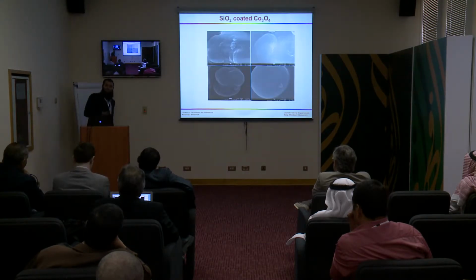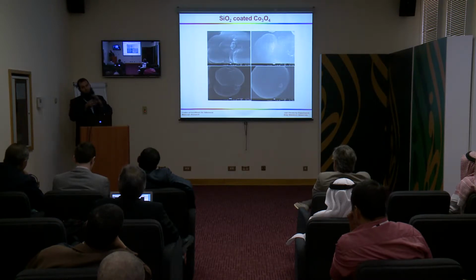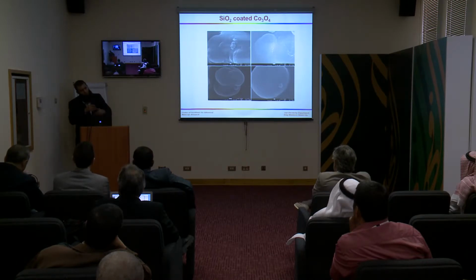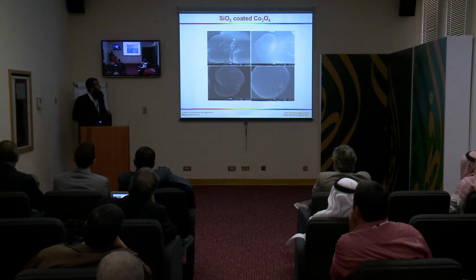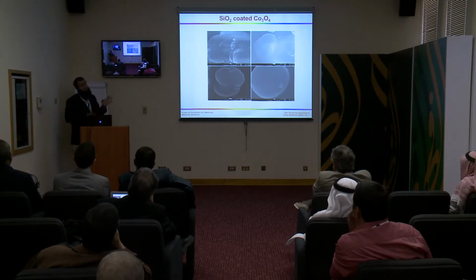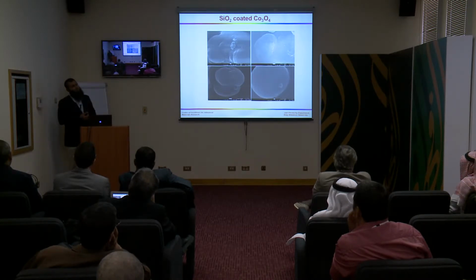Then we tried to make a cobalt mesoporous material by following some literature. In that case, they made a core shell using the nanomaterial coated with silica, and then coated it with polymer. After that, they extracted the silica and made a core shell. We tried that, but we did not succeed. We coated the cobalt oxide with the silica, but we did not succeed in getting the polymer chain around the material.